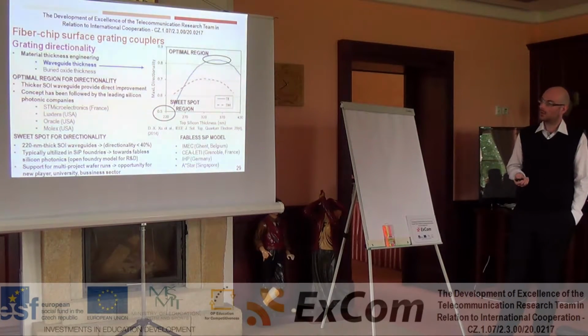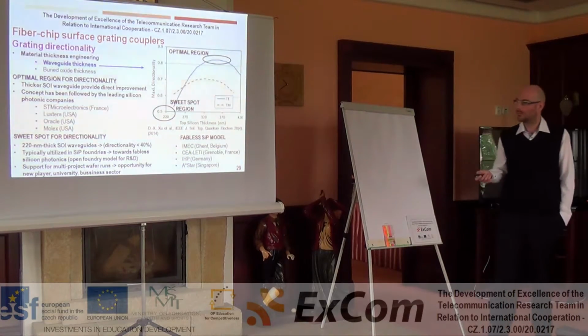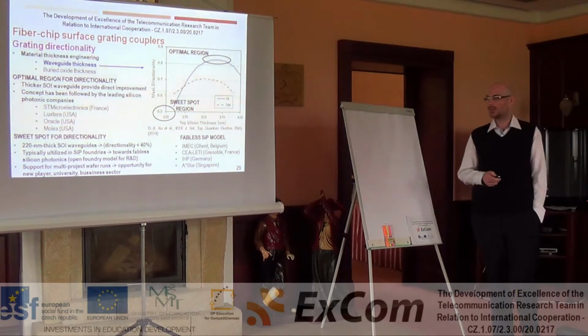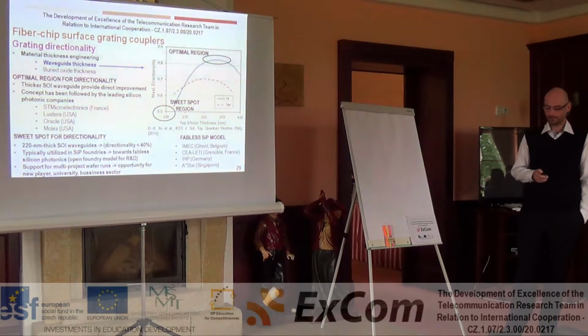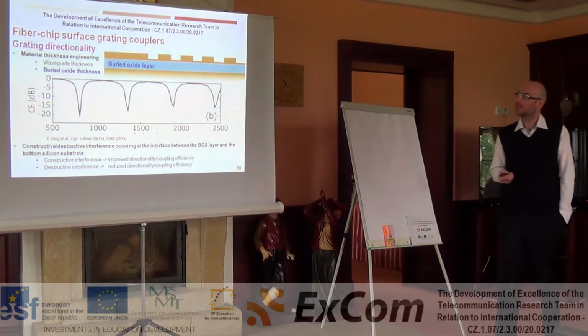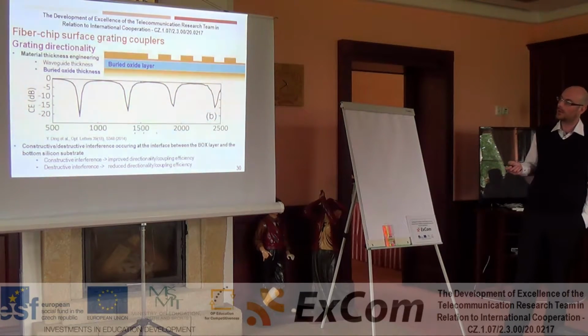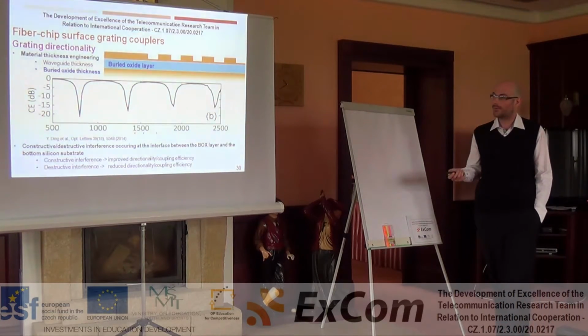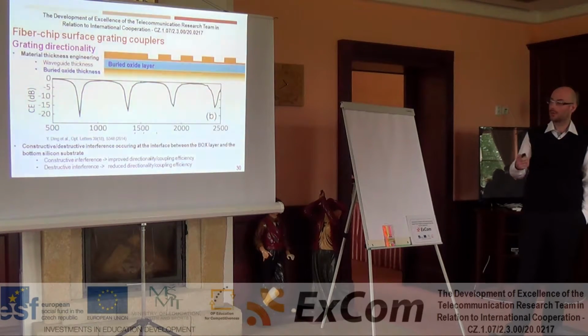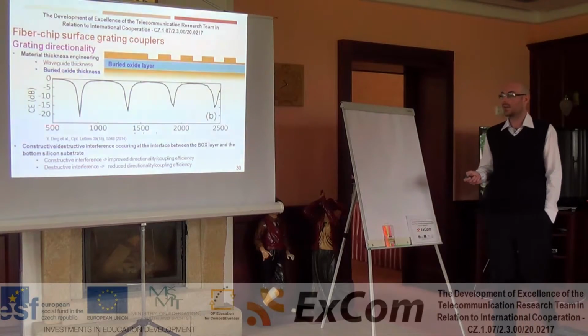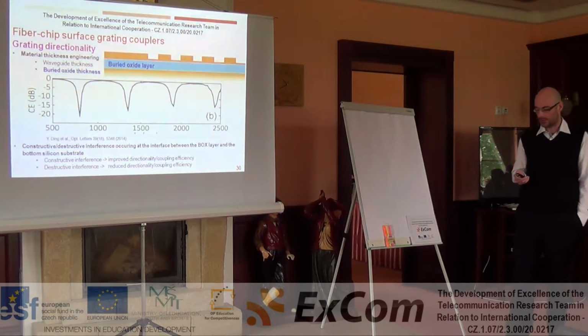This fabless silicon photonic model has been implemented by European companies such as IMEC, CEA-Leti in France, IHP in Germany, or the company A*STAR from Singapore. The second issue in terms of grating directionality is the thickness of a buried oxide layer. By changing the thickness of this layer, the constructive or destructive interference effect can occur at the interface between this box layer and the bottom silicon substrate. If we have constructive interference, we can have very good coupling efficiency, but on the other hand, if we have destructive interference, we can have very low directionality and very low coupling efficiency.